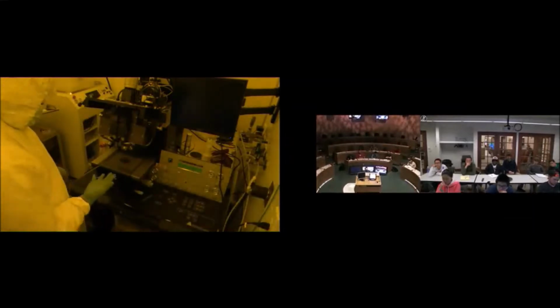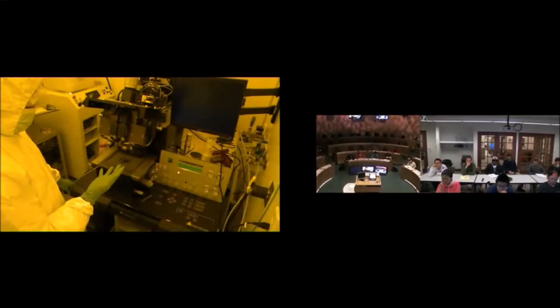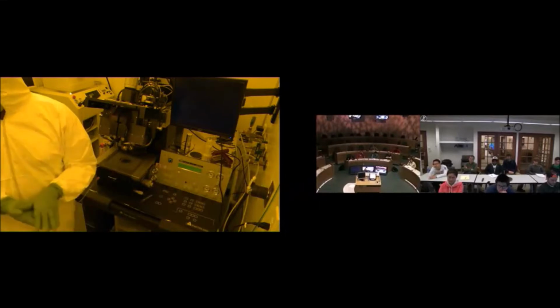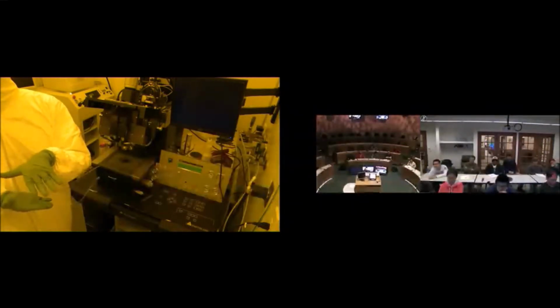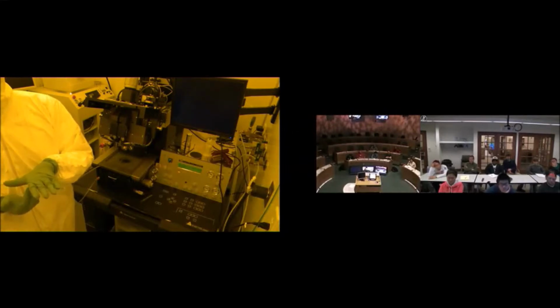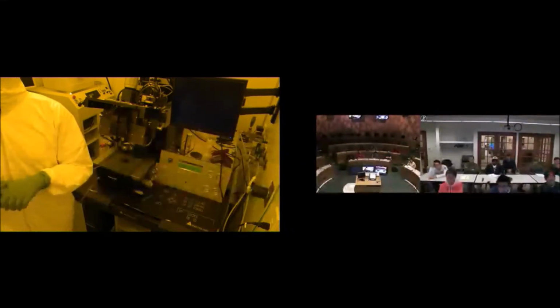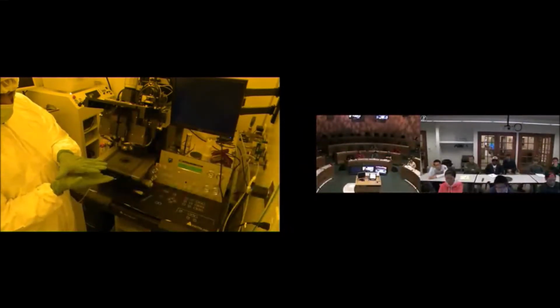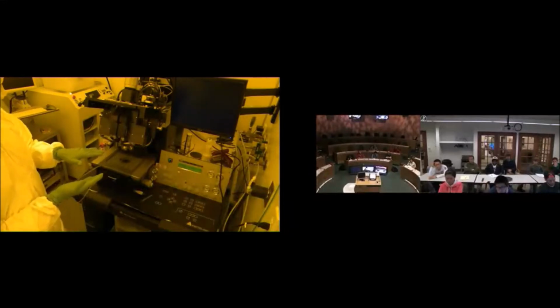So what it's doing is going to raise the wafer up towards the photomask, and it's going to do what's known as a wedge error correction. They're saying performing wedge error correction. That's basically, if you got a mask here and the wafer here, they got to be perfectly parallel. If there's some kind of wedging, a tilt between the two materials, the mask and the wafer, you have a gap, and the gap is not even. So it's one thing to have a gap, and it's even worse to have an uneven gap. So it's just creating an even gap, and now I can expose it.